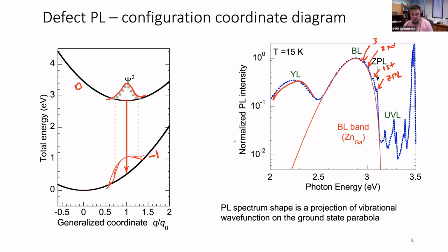in a few minutes. So what I'm saying is, if these two defect charge states, 0 and -1, are separated by a large configuration coordinate Q, you usually get these very wide PL bands. If they are not separated by a lot, they're basically right on top of one another. That's usually the case for shallow defects. You get this very, very sharp PL band where the ZPL is a very high, very well resolved peak. The first phonon replica is well resolved, second phonon replica, and so forth. And if it weren't for this band that covers it up, they would keep going farther and farther. So how far these parabolas are separated from each other, in other words, how much the crystal lattice is different for the -1 and 0 charge states, affects the width of the photoluminescence.